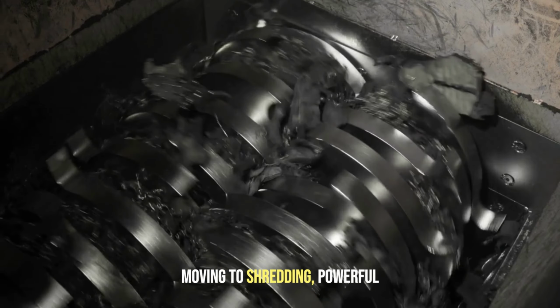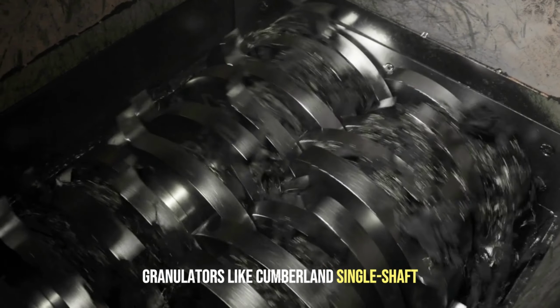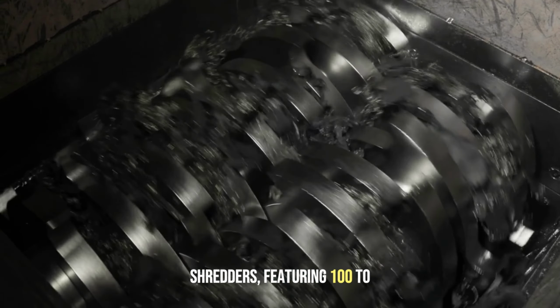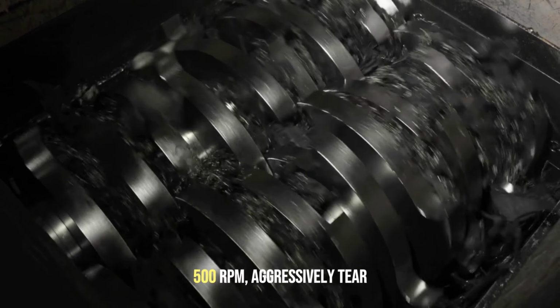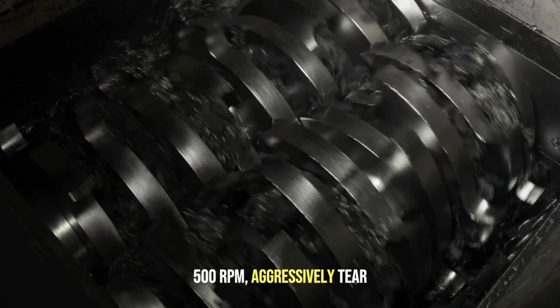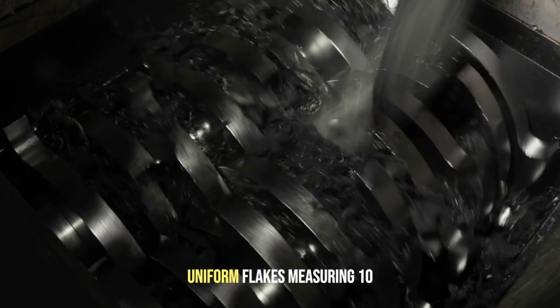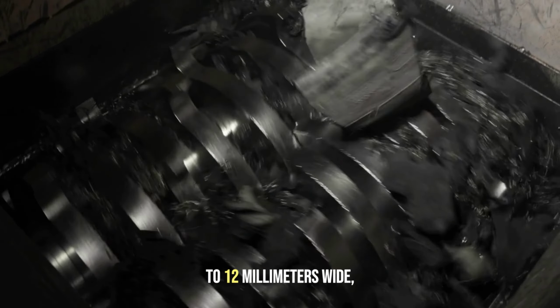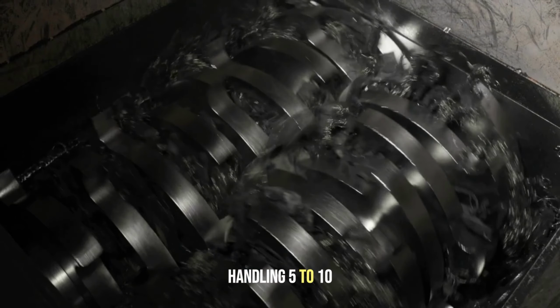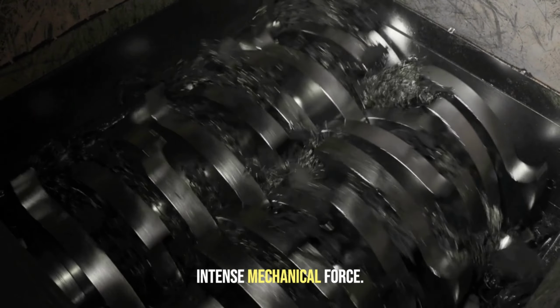Moving to shredding, powerful granulators like Cumberland single-shaft shredders, featuring 100 to 200 rotating steel blades spinning at 300 to 500 revolutions per minute, aggressively tear the sorted plastics into uniform flakes measuring 10 to 12 millimeters wide, handling 5 to 10 tons per hour with intense mechanical force.